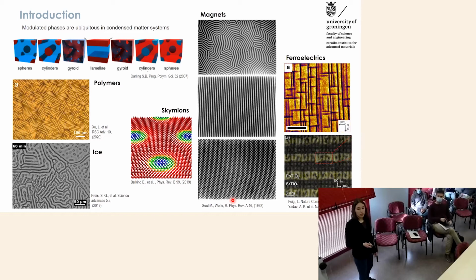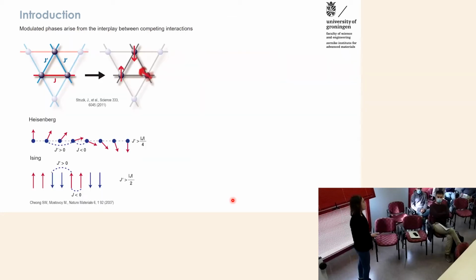So we are interested in these systems from a general, fundamental point of view. In general, how do these modulated phases and periodic patterns arise? Usually they arise as a consequence of the presence of competing interactions. Here, for example, you can see some magnetic materials where we have different exchange interactions between the component spins of the system. In this case, where we have hexagonal lattices, we can have spins which are coupled through a magnetic exchange which is antiferromagnetic, and will tend to align all the spins in the lattice antiferromagnetically with each other. But due to the geometry of the hexagonal lattice, it's impossible to satisfy all the competing interactions and have all the magnetic exchanges satisfied.